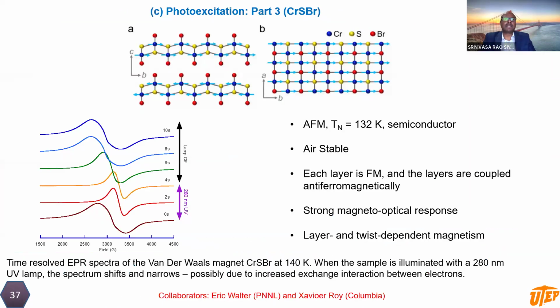So we are conducting additional measurements on another important layered antiferromagnetic material, chromium sulfur bromide. And here I show our initial data. This is the electron spin resonance signal. Before we shine light on this crystal, we use a UV lamp of about 280 nanometers, and then we shine light on this crystal and see how the electron spin resonance signals evolve as time progresses upon photoexciting this crystal. After about 10 seconds, the signal comes back to its original pristine state. During this time, you see how the signal narrows, how the signal moves towards the original position, and the shape of the signal also changes.